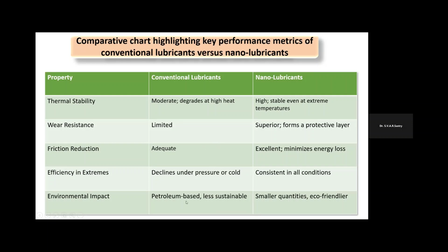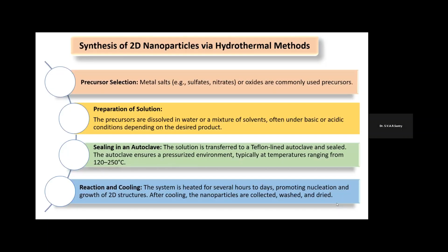The conventional lubricants are based on petroleum-based feedstock, therefore they have a higher environmental impact and they are less sustainable. Whereas the nanolubricants can be used in lesser quantities and also they can be made from biodegradable biological resources like castor oil, neem oil, etc., which are non-edible oils, and thus they are also environmentally friendly. So how to synthesize the nanolubricants and how to add the two-dimensional nanoparticles, and which method we should take into account. So the hydrothermal method for synthesizing nanoparticles is found to be the best method as of now, which can be used to make the nanoparticles, and then the nanoparticles can be added as additives in the lubricants.